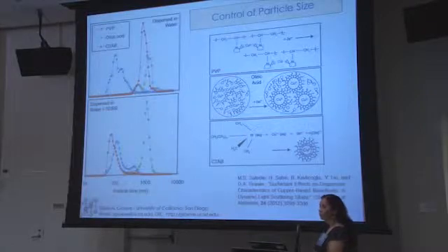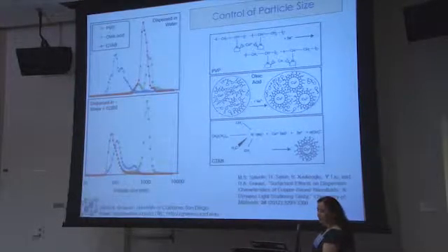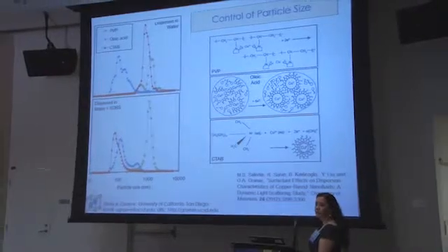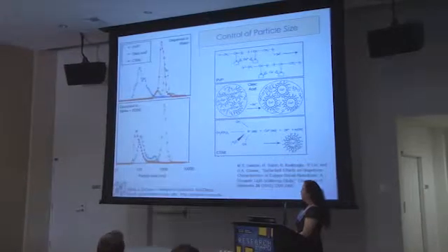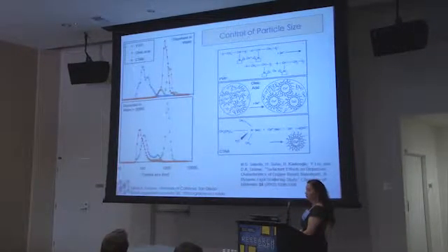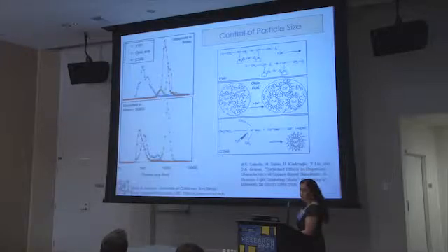In my research group, we have acquired significant expertise in a technique known as dynamic light scattering. This technique allows you to measure the size distribution of agglomerates. The picture on your left is one of those distributions. It happens to be the distribution of particle size, or agglomerate size if you like, either is a good name, of a copper powder that has been dissolved in water with a variety of surfactants.